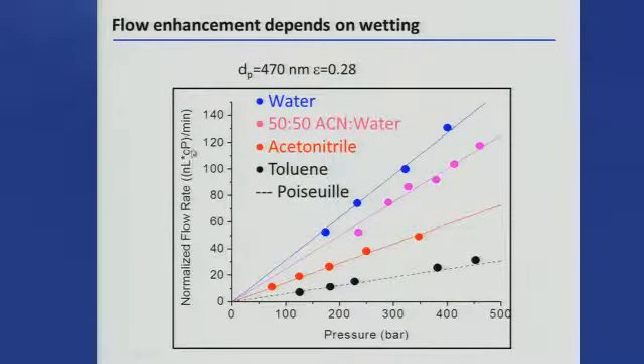And the flow rate's normalized here for viscosity. So if you normalize for viscosity, if nothing funny's happening at the interface, all of these should line up, because that's the only thing that affects the flow rate. And what you can see is that water has the highest flow rate when you normalize for viscosity. Toluene has the lowest. Toluene is the one that would interact the most at the hydrocarbon surface, and this dotted line is the theoretical prediction for the Poiseuille flow.